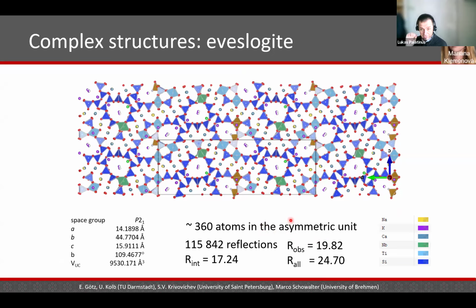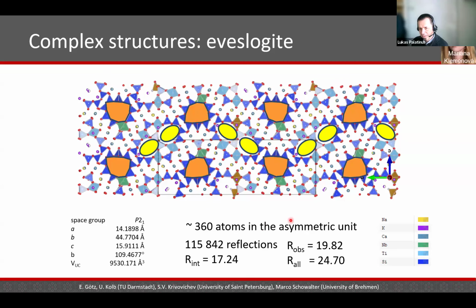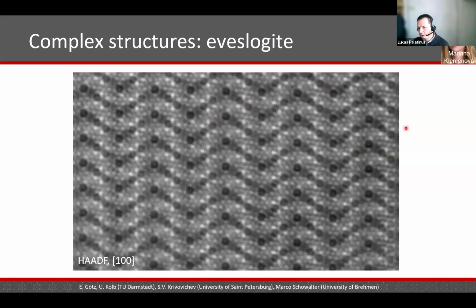And the nice bonus in this investigation was that a colleague from Germany was able to collect high resolution transmission electron microscope images. And these, okay, sorry, I forgot to mention that this is some kind of a nanotubular material which forms channels along this direction. But then these are the high resolution images. And you see the first stunning thing for me was that there are no defects here. Everything is perfectly ordered. Despite the incredible complexity of the structure, there are no stacking faults, nothing like that